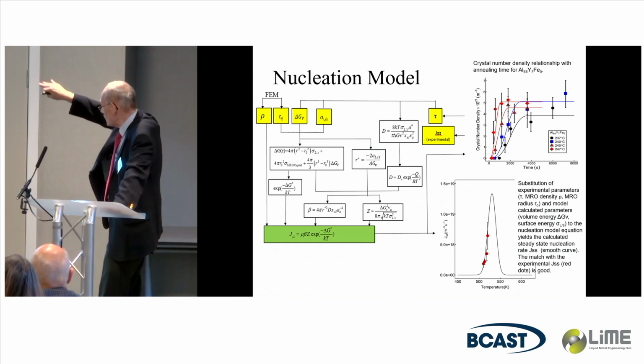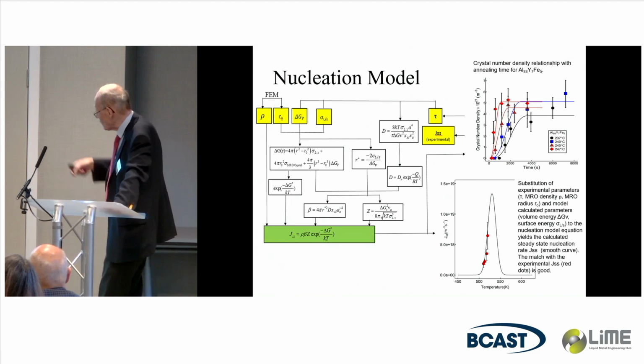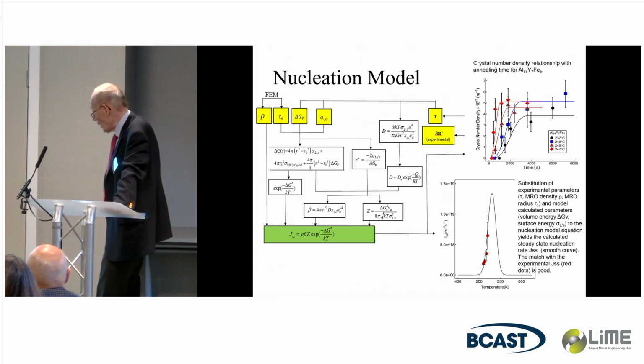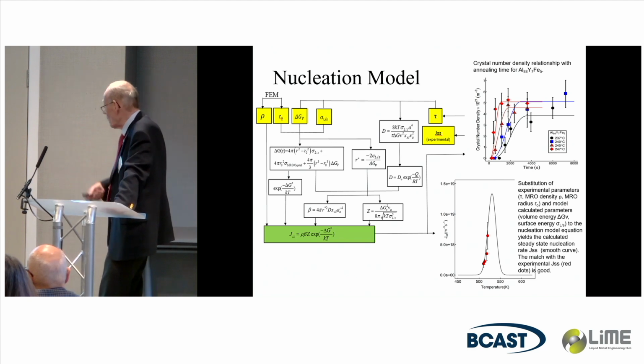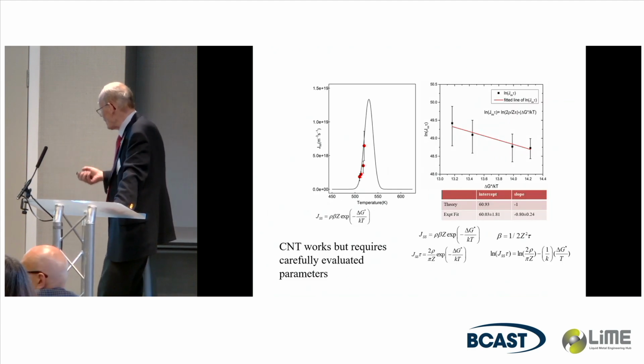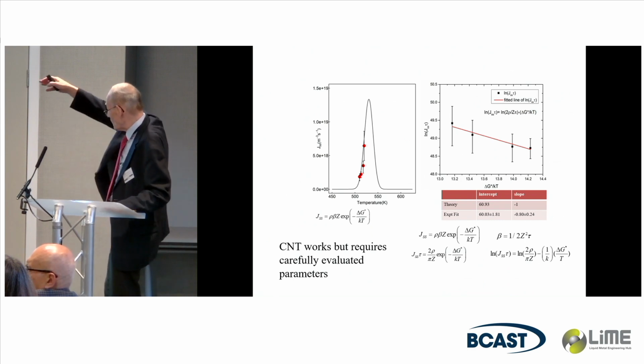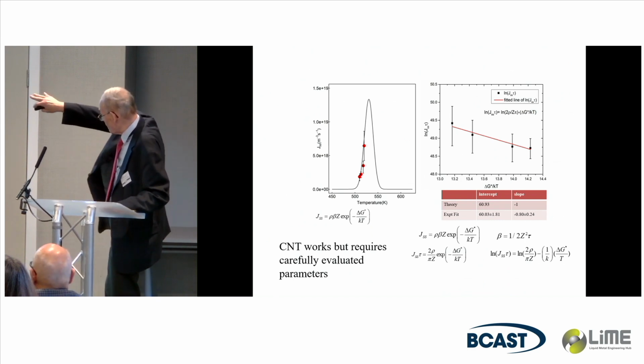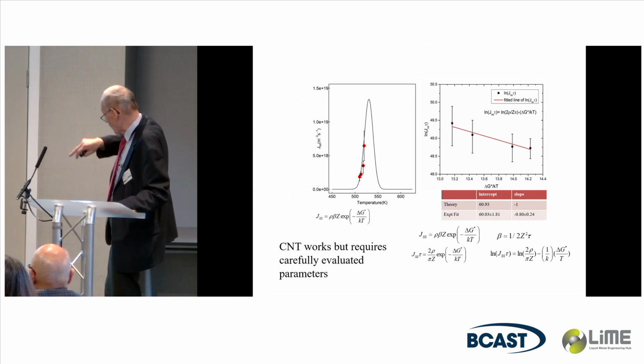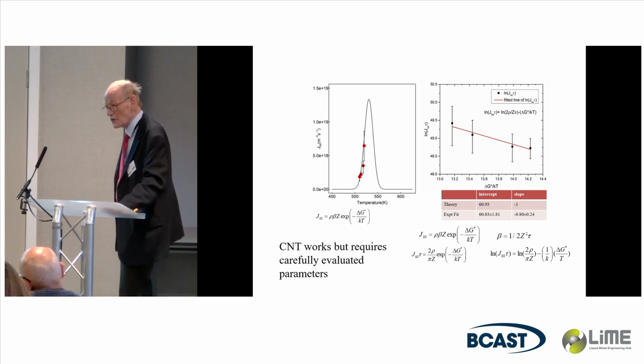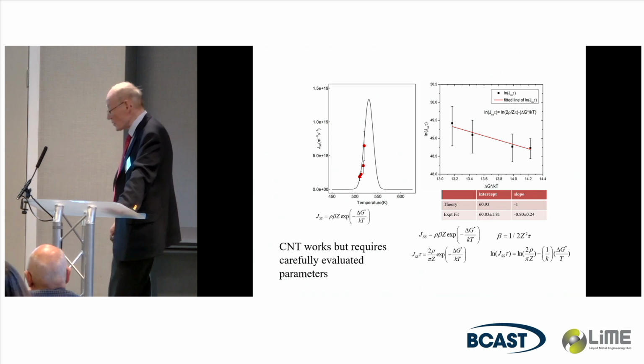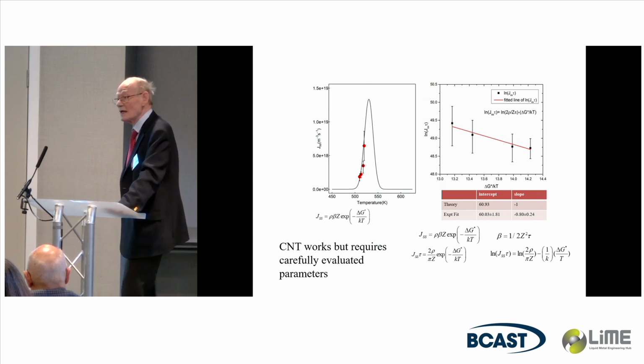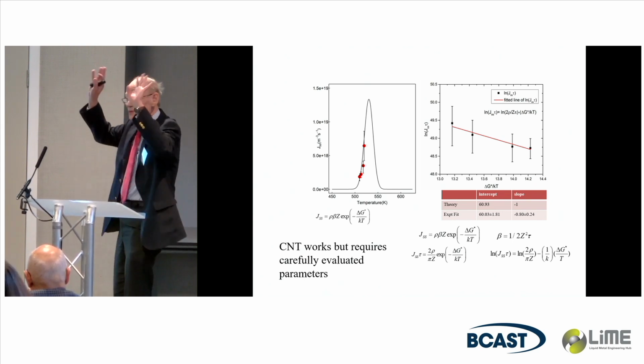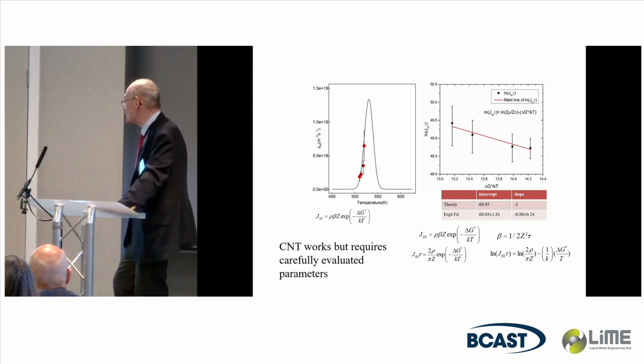The curves fit our experimental points very nicely, and we've gone through the whole analysis, carefully documenting each step. And when we do that, we have, Lindsay should be here, an independent test of plotting the log of the nucleation rate times the delay time versus delta G star over kT. There's good agreement between the theory and the experiment. So classical nucleation theory works, but you have to evaluate the parameters carefully. A lot of people take gross approximations and they say theory failed. Well, that's not quite true.